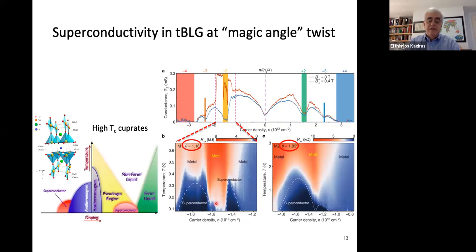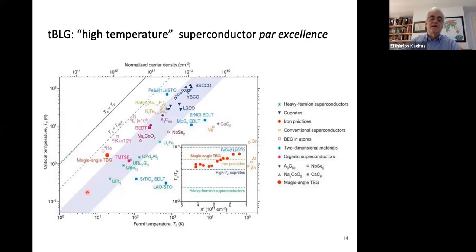And there's definitely a lot of similarities with the phase diagram of high Tc cuprates with superconducting phases, metallic phases, and insulating phases, the antiferromagnetic phase, and so on. So this created a lot of excitement. Moreover, it was suggested by work that the twisted bilayer graphene is actually a high temperature superconductor par excellence. And what is meant by this is that if you plot the critical temperature versus the Fermi temperature, and this is a measure of the number of electrons, you realize that this is where twisted bilayer graphene lies. And the ratio of those two numbers is higher than it would be in the various copper oxides. So here's in the inset, again, a plot of this ratio. And here are the points for graphene.